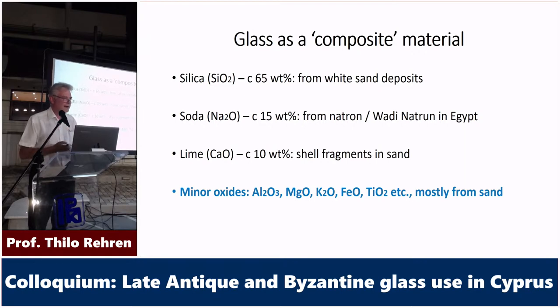You have a brine that in the summer dries up and creates a white salt, which has a specific composition that it can melt with the silica to make glass. With the silica sand, typically, that you get from the beach, you get fragments of shell, mussel shells and other stuff, which add lime to the picture, calcium oxide. That's 90-95% of your glass. And then there's a little bit of spice in it, minor oxides, which come with the sand.